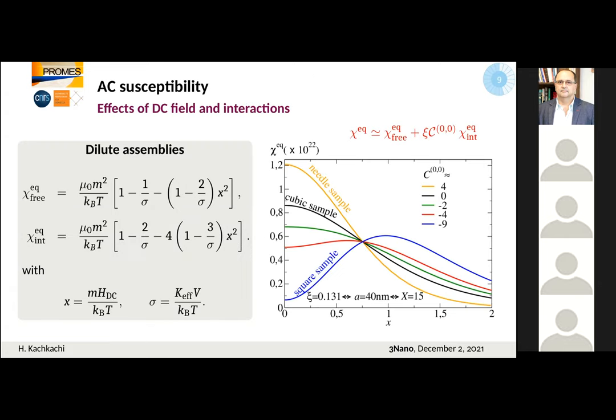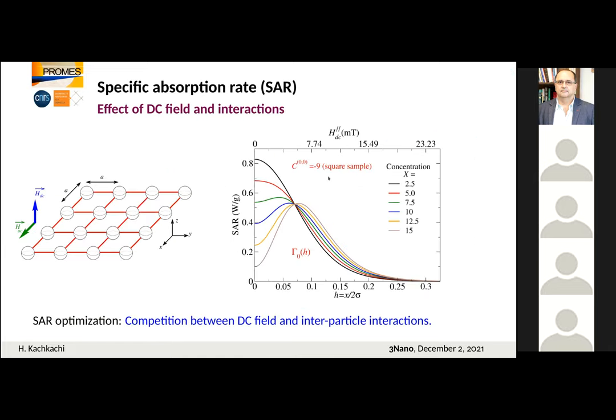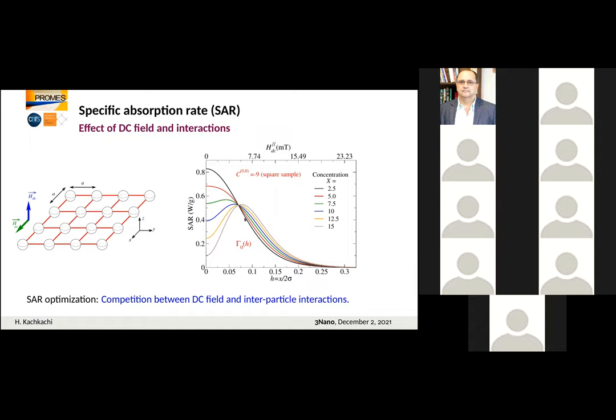But another very important point is that, depending on the concentration, we can see that the maximum of the SAR, if there is a maximum, changes with the field. This means that there is a competition between the DC field and interparticle interactions. Because in the literature, people think that if we increase the concentration, we will enhance the SAR. This is not really true. This depends. There is a subtle interplay between the DC field and the concentration.